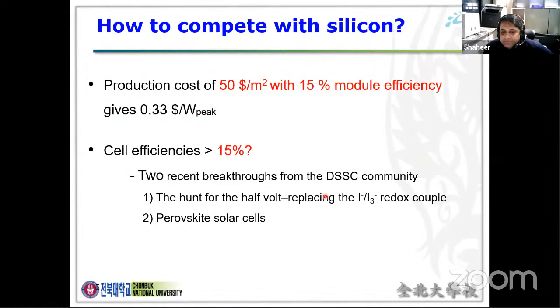So there are two possibilities in thin film solar cells, essentially the dye-sensitized solar cell and perovskite solar cells. In dye-sensitized solar cells, if we replace the traditional iodide coupled redox electrolyte by using a half voltage electrolyte like a cobalt complex, using cobalt 2 and cobalt 3 couple based electrolytes, we can improve the performance, and then we will reach an efficiency of over 15%.